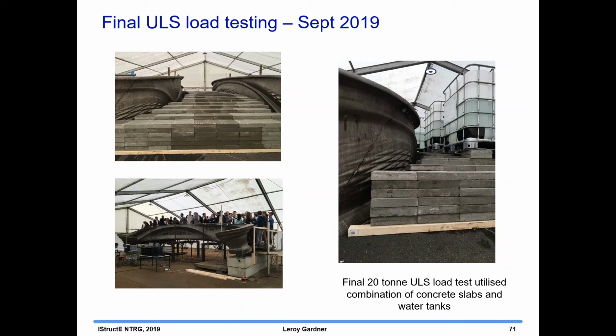So at that stage, we put some water tanks on, and we increased the load by a further 5 tons. We then took the water off again and put the final 2 layers of blocks in place. That then took us up to a load level which was still below what we'd had with the water in place. And then we put the water tanks back on and took up to the full ultimate limit state design loading, but without us being on the bridge at the time. We put some students on the bridge because we weren't so worried about them.